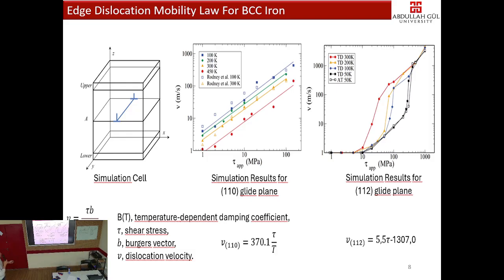Please look at this graph. This is for edge dislocation, literature data without any hydrogen, just edge dislocation with different temperature and the speed of dislocation. As you can see, the lattice resistance for edge dislocation is pretty low. 10 megapascals, 3 megapascals. We have mobility of these edge dislocations, right? Since it's phonon drag. But please check, once you increase the temperature, whether the velocity of dislocation increases or decreases.